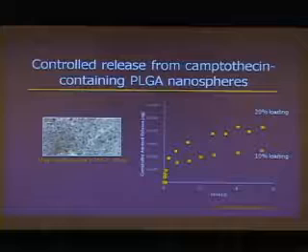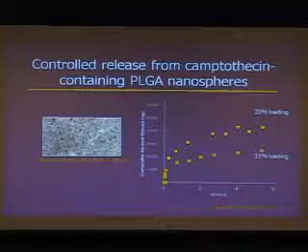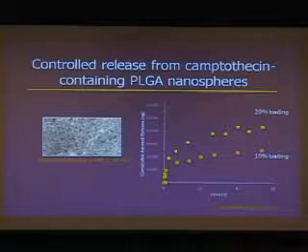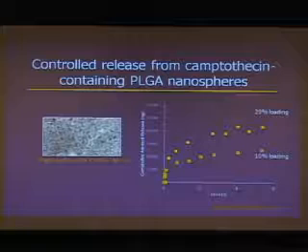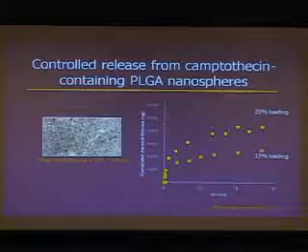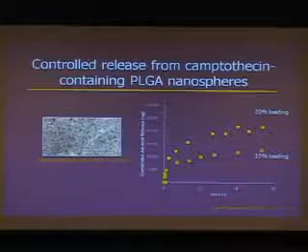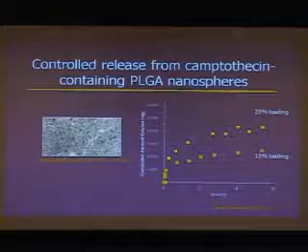It took us about 6 or 7 years after that to decrease the size by about a factor of 10. These are particles that were made by Amaryllis Sanchez at Cornell. She was a graduate student who worked with me there. These are particles that were unique at the time for a couple of different properties. One is that they're quite small. These are 160 nanometers in diameter, so roughly the size of a virus. And they're fairly uniform. They're small and discrete particles that can be easily resuspended in solution.